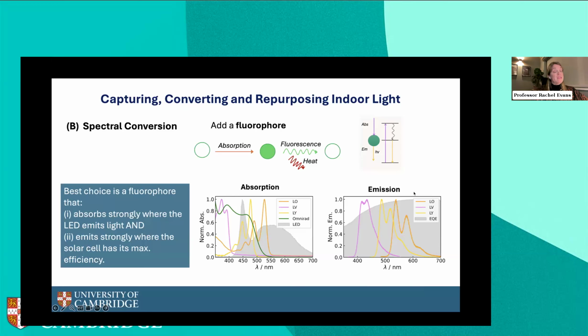So if we look at these two graphs here, we can see in the absorption graph, the gray area is the output from our LED. And then in the emission graph, the gray area corresponds to where our solar cell performs best. And all of the other colored lines are basically the absorption and the emission from different fluorophores or light-emitting molecules. And hopefully we can see that the orange line in this case gives the best compromise, the best of both worlds. So we get the maximum absorption and the maximum emission where we need our material to work.